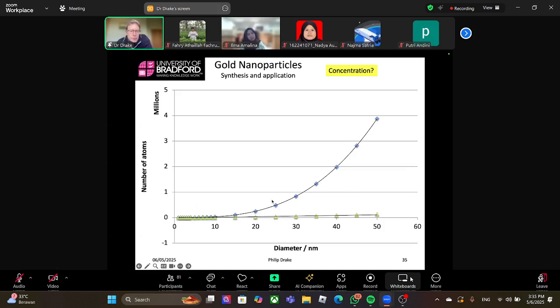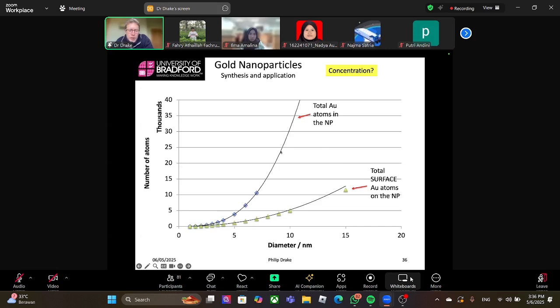We can plot two numbers. The blue line is total number of atoms in the nanoparticle. The other line is surface atoms. So what's important with nanoparticles is the ratio of surface atoms to core atoms. As you get smaller, the number of atoms decreases, the number of surface atoms becomes closer and closer to the total. So a 10 nanometer particle has about 35,000 atoms in its core. It has about 5,000 on the surface.